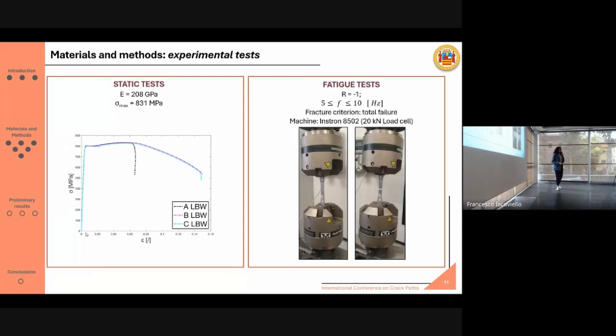Concerning the fatigue tests, they were tension compression fatigue tests, so R is equal to -1, with a frequency comprised between 5 and 10 hertz. And here you can see a picture of the specimen mounted into the instrument belonging to our lab and a picture of the same specimen after the end of the test.